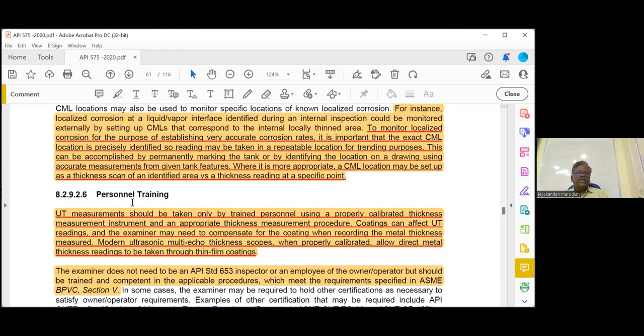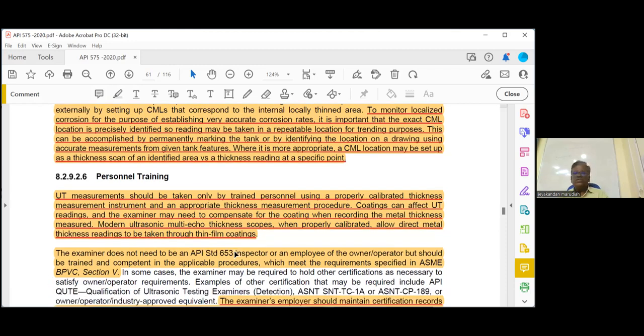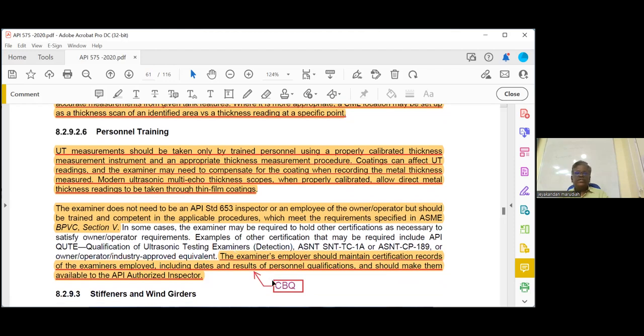So highlight the 8.2.9.2.6. UT measurement should be taken only by trained personnel using a properly calibrated thickness measurement instrument and an appropriate thickness measurement procedure. Coatings can affect UT readings, and the examiner may need to compensate for the coating when recording the metal thickness measured. Modern ultrasonic multi-echo thickness scopes, when properly calibrated, allow direct metal thickness reading to be taken through the thin film. Then this is important.